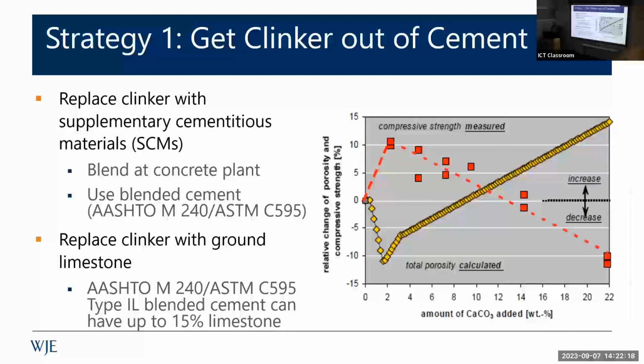And the reason they selected that is actually, when you start to put in limestone and you intergrind it with clinker, you actually get a more optimized binder, and you see an improvement in strength and a decrease in porosity. And up to about 12 to 13%, as the chart there shows, in this case, you're about even with where you started, and that's how that number was selected.